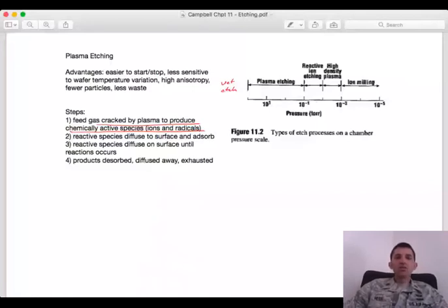At any rate, the etchants are also selective with respect to crystal direction, which should intuitively make sense when you're talking about breaking bonds, right? The distance between atoms and the strength of the bond differ depending on what crystal direction you're talking about. Okay, and different etchants can also select for doped regions, so if you know well the etch rate as a function, say, of defect or doping level, then you can actually use that to characterize your device. Okay, so that's chemical etching.